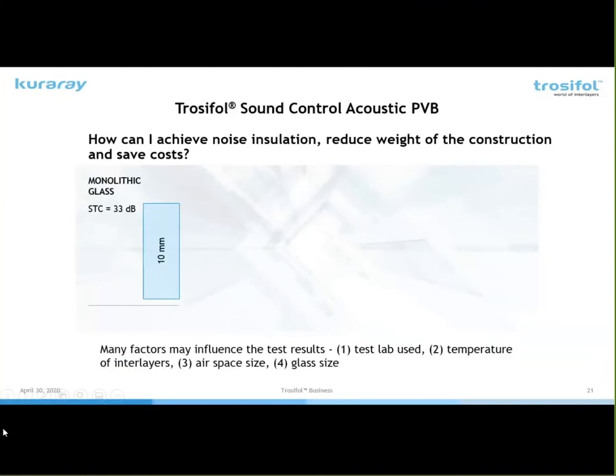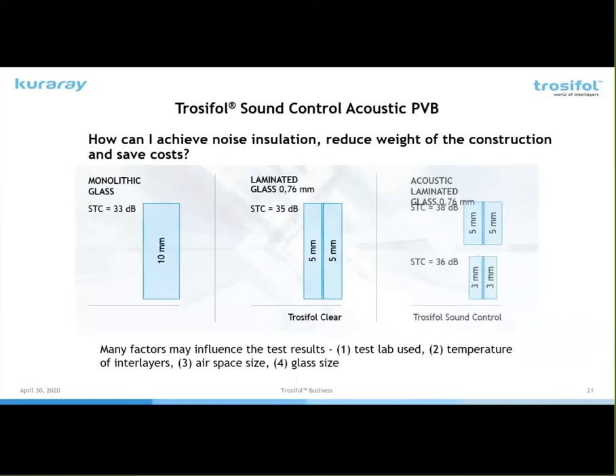So this is what your thought process may be when you're designing some acoustic glass. You can look at a monolithic piece of 10 millimeter glass and get an STC rating of about 33. Now, if you put in laminated glass with two 5 millimeter pieces of glass and a standard PVB, you could increase that performance to a 35. If you put in a laminated glass with an acoustic PVB and the 5 millimeter glass, you can go up to 38. So you go 5 points from a monolithic glass to an acoustic PVB.